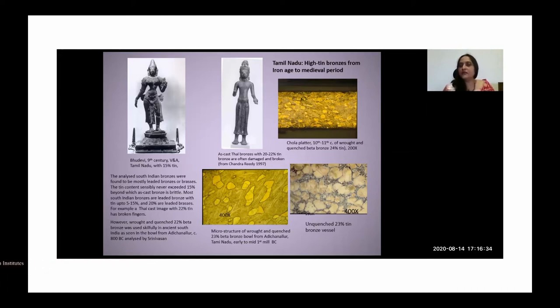But what is remarkable about the beta bronzes is that although they had 23% tin, this is because of the fact that they are forged at a high temperature, which maintains the presence of this beta phase, and then they are rapidly quenched so that there is no embrittling alpha plus delta eutectoid formed.